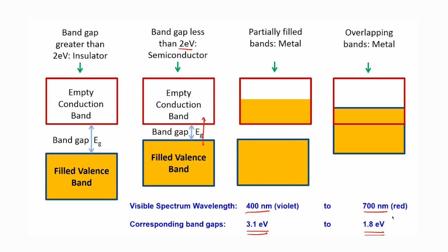What will happen? Interestingly, the higher energy radiation, which is 3.1 electron volt radiation, gets absorbed by the material because it is possible to do this transition that I just showed you. Even though the band gap is only 2 electron volts, the 3.1 moves the electron into the conduction band, because it has more energy, it pushes the electron above the starting point of the band, and then maybe some other things will happen, let us not worry about what happens at that point.